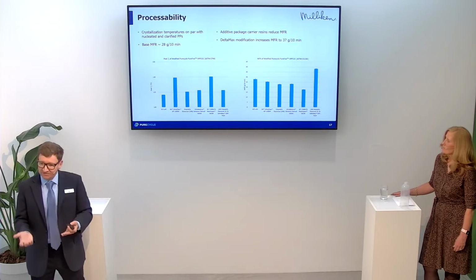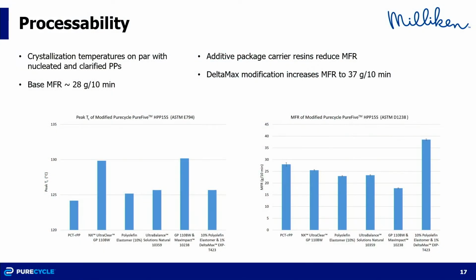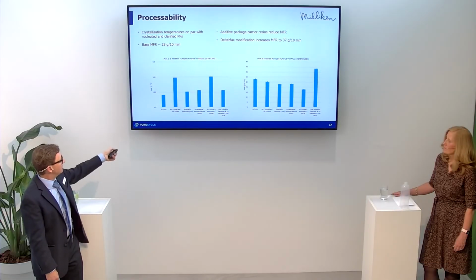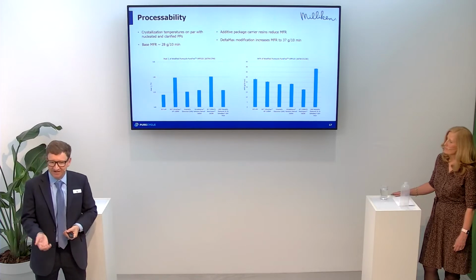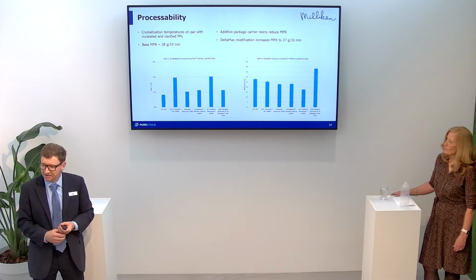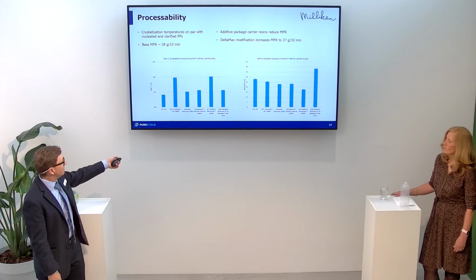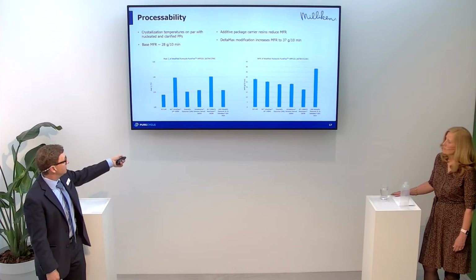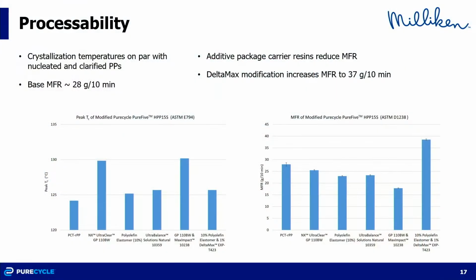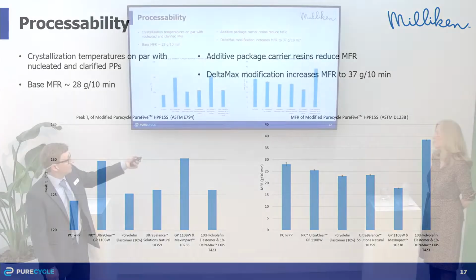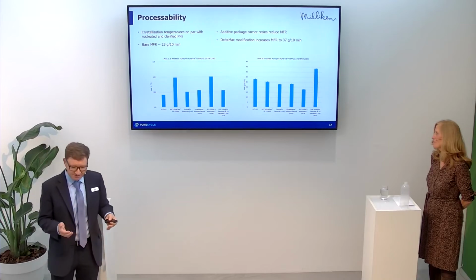So first looking at the thermal and processability of these materials. On the left here, I have peak crystallization temperature, and then here are all the samples that we looked at. And I'll say that their base material with the Milliken nucleating package is about 124 degrees C, which is pretty common for nucleated polypropylenes. The two samples with the NX8000 are a bit higher at 130, and then also the same 125-ish for the other nucleated samples.